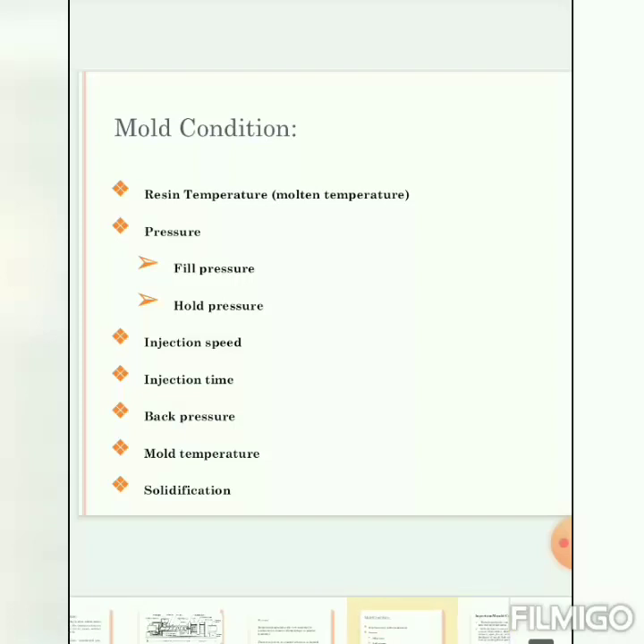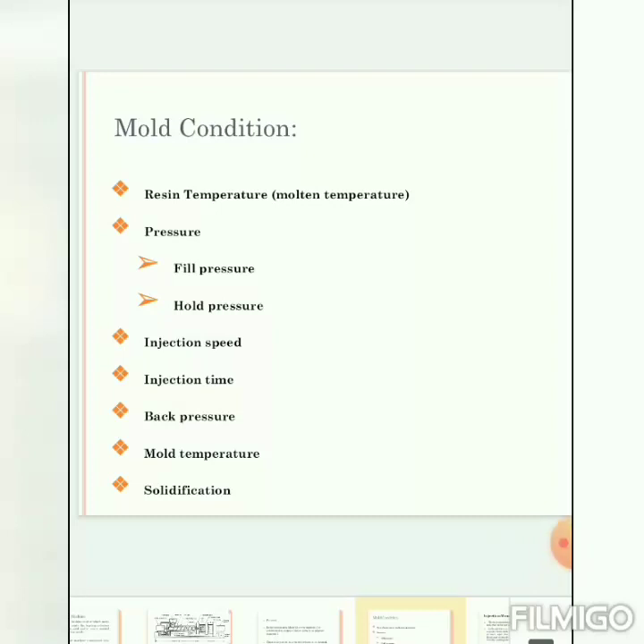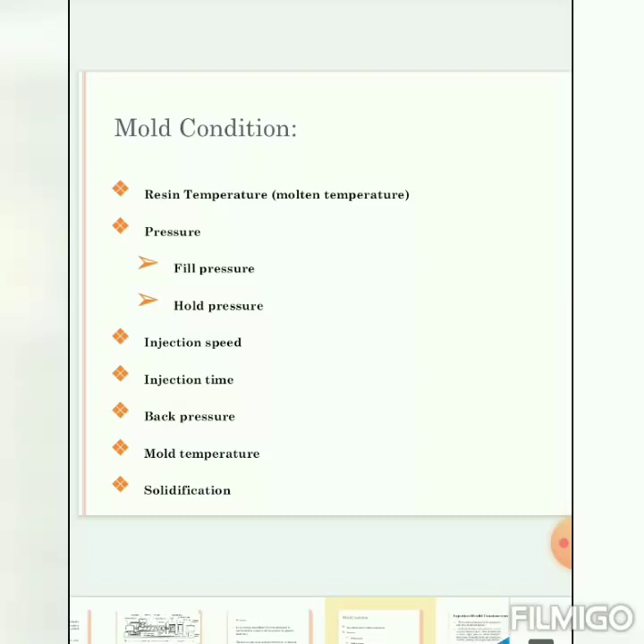Injection speed plays a very important role during the molding cycle. For thin or small thickness products and multi-cavity molds where precision is required, faster injection speed gives better results. Injection time is set as per different machines and part sizes and shapes. It is considered as the summation of filling time plus pressure-keeping time, and it should be greater than the time for material to stop flowing by solidification at the gate.